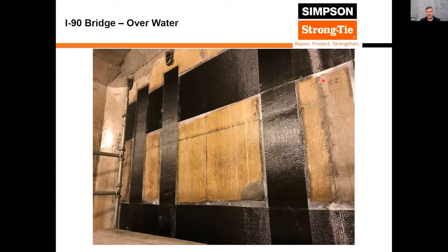But the reason that you want to feather all those edges is, well, for one, they'll protect the FRP edges during cure and throughout the rest of construction, so nothing catches that edge and starts to peel the FRP. But also they're there holding down the edges of the FRP, preventing stress concentrations from debonding the FRP. So if you had a portion that wasn't feathered, say down at the end of this strip or up at the end of this strip, and the FRP went under load and it wasn't completely feathered out on that edge, you could have a stress concentration that starts to peel the FRP off. It's very important that all the details and specifications are met with FRP and everything's done 100% as required.